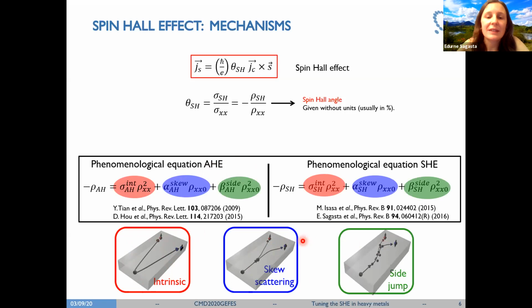We used this phenomenological equation in our group for the first time to explain our spin Hall effect results in platinum. So an important note here is that if we are able to determine which mechanism is dominating the spin Hall effect, this will tell us how we can enhance the spin Hall angle.